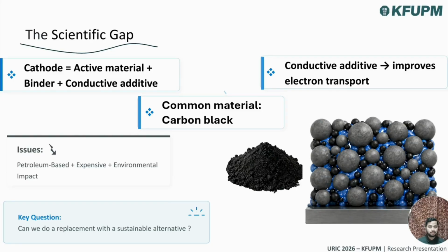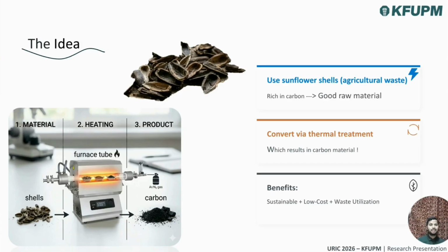So now when we want to discuss the cathode, the cathode usually consists of three main things: the active material, which stores the charge, the binder, which connects everything in the battery, and the conductive additive. The conductive additive is the one that is moving the electrons. And the common material is carbon black. Carbon black is petroleum-based, which is environmentally harmful. Also, it's expensive. So we came up with an alternative material, which is sunflower shells. Sunflower shells are rich in carbon, so they're a good raw material as a replacement for carbon black, and they will be converted to activated carbon through a thermal process.